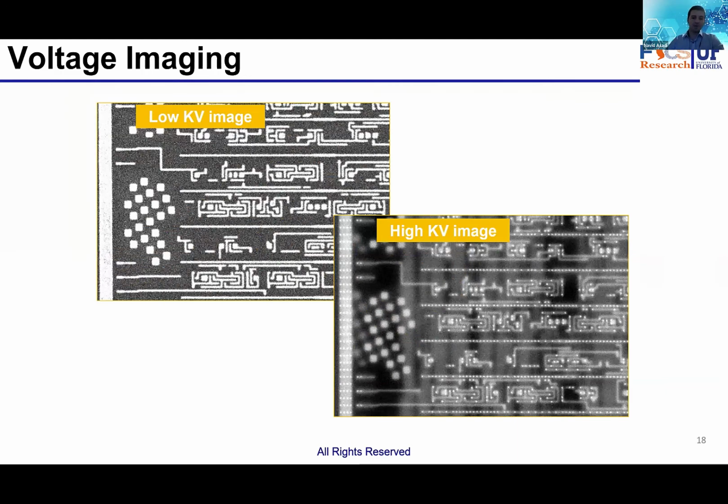They're right now collecting images at the nanometer scale, delayering, going to the next layer, and then doing the imaging again. There was a program by IARPA called Raven 4 or 5 years ago, with millions of dollars of funding to make this faster and faster. So new SEMs were developed to collect images, and instead of using 1 beam, actually using even more, 60 or 90 beams, or a distribution of the beam, to collect the images.